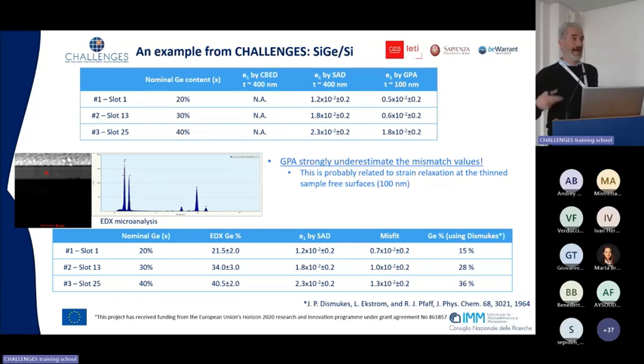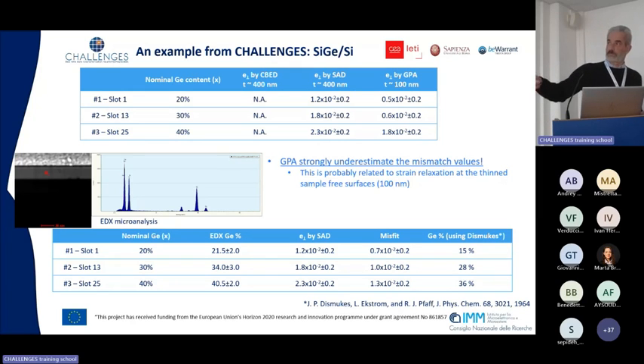At 100 nanometers, our microscope is not able to record a good high resolution image. So we have to keep it thin. We have the thickness of our sample. Okay, the first candidate for this discrepancy is strain relaxation, in my opinion, but we wanted to check it. We also performed microanalysis, and the result was quite good, because 20 and 21 by EDX, 30 and 34 by EDX, 40 and 40 by EDX, so it was not bad.